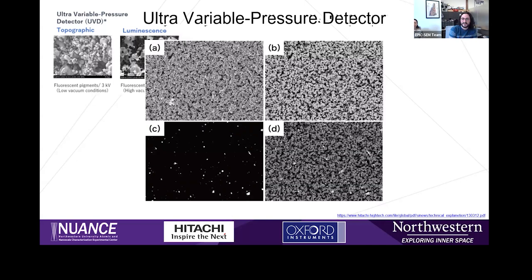B is going to be a backscatter image of the same area, and you can maybe convince yourself that there's some areas that look brighter, but not really, right? It's all the same material. But if you take a look at C, that's the CL image using the UVD. You can clearly see the anatase particles lighting up because they have a higher CL luminescence than rutile. And by overlaying them on the BSE image in D, you're able to tell where your particles of interest are pretty easily.